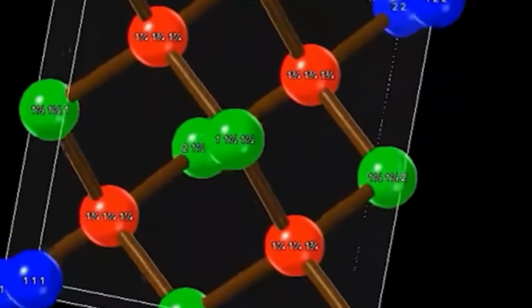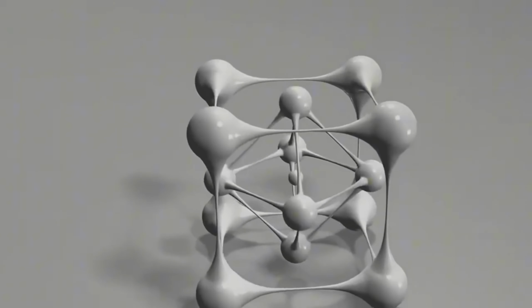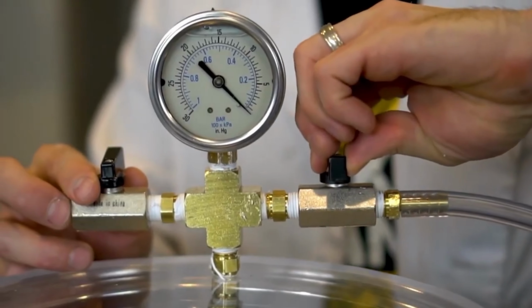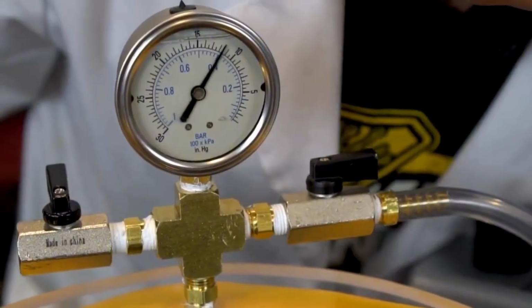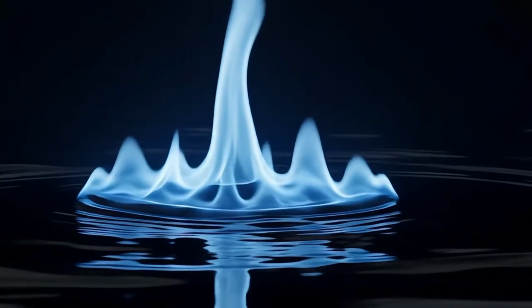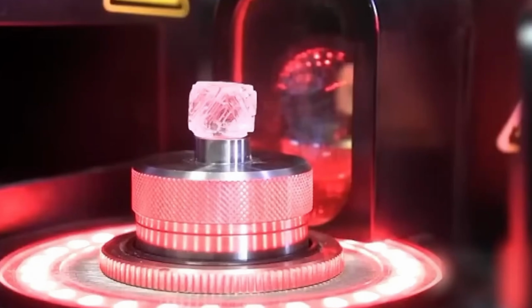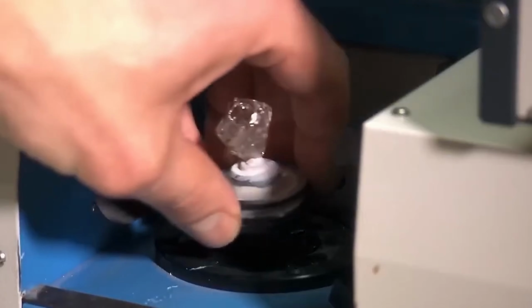Microwaves or radio frequency energy ionize the gases, forming plasma. Inside this plasma, methane splits apart, releasing carbon atoms. These carbon atoms slowly fall onto the diamond seed and bond to its surface in perfect cubic layers, expanding the crystal vertically and horizontally. The process functions like molecular stacking, microscopic layers accumulating one after another.